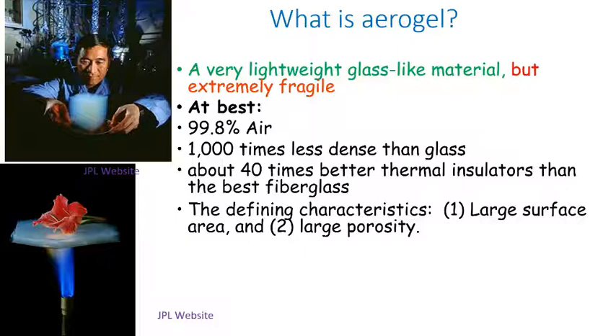This is one type of aerogel that this gentleman is holding. It's actually from JPL, the Jet Propulsion Lab. And this is called silica aerogel. The silica aerogel that you see here can be made up to 99.8% air. We have made one that was like 99.2% porosity. This is the porosity. The other characteristic is that it can actually be 1,000 times less dense than glass, because glass is made of silica, right?